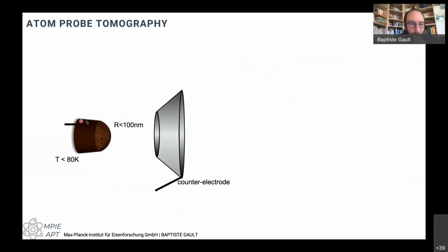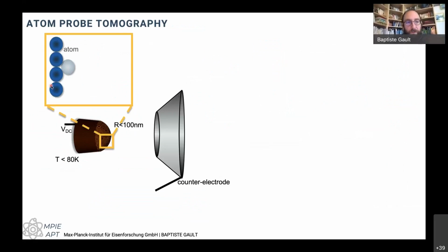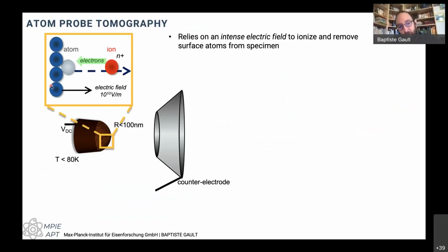And then we stick that needle into an ultra high vacuum chamber, so in the range of 10 to the minus 10 to 10 to the minus 11 torr. We have this very sharp needle. We cool it down because we don't want the atoms to start moving around. During the experiment, we want them to stay still. And then we apply this high voltage. The surface atoms will progressively turn into ions, and they're being projected away along trajectories that are defined by the shape of the needle and pure electrostatics, right?